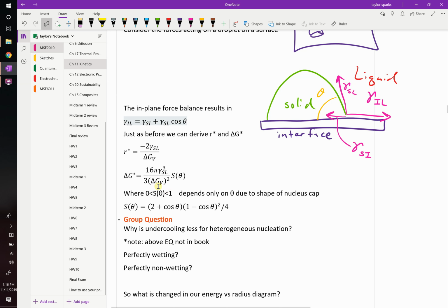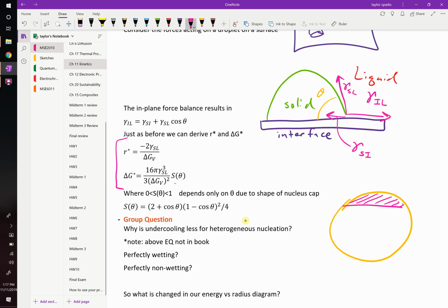Because once you know your wetting angle, you can calculate S of theta, this term here. And all that is somebody did the geometry for you, and they basically said, if this is a perfect sphere, you can take any sort of spherical cap of that, and this will tell you the surface area to volume ratio, right? So that S of theta, if you look at our expressions from before, these things look the exact same as before for homogeneous nucleation. The only difference is that they've been modified by this S of theta, right?